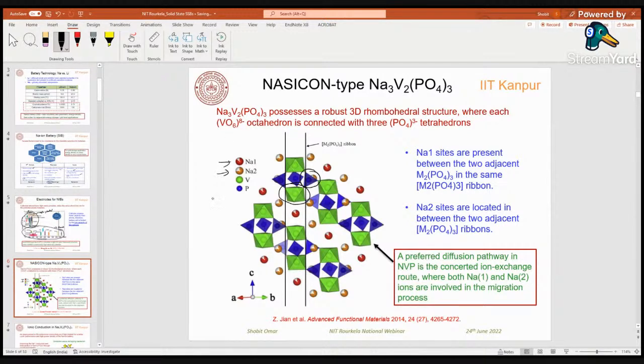They are 2 different sites, and one can see that this is a rhombohedral structure, and here Na1 is basically present between the 2 lantern-type structures. This is a lantern-type structure, what we call, and it's called M2(PO4)3, and this Na1 site is present in between the 2 adjacent lantern structures, whereas Na2 is present between the 2 adjacent ribbons. This is one ribbon-type structure, right? So Na2 is present between the 2 ribbons, while Na1 is present between the 2 lanterns. Okay, so this is how you describe the NASICON structure of NVP, I should say.